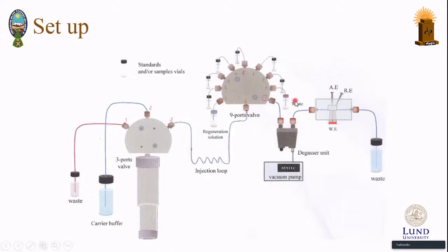In this second valve, in number 1, we have the regeneration solution. We can use 6 standards or 6 samples. We have the waste, and then the most important part, where we go to the flow cell. Before going to the flow cell, the sample must be degassed, as gas can affect the measurement of the capacitance. This flow cell is based on 3 electrodes: the working electrode, with our insulating layer and our biorecognition element on it, the auxiliary electrode, and the reference electrode. And finally, when the detection occurs, it goes to the waste.